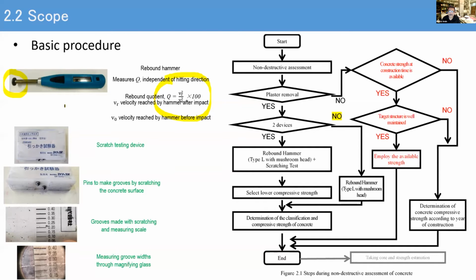And it's not a new device we propose here. It is actually commercially available from many renowned manufacturers. So we chose this device. Another device we chose here is the scratching testing device. It is basically based on the groove width. We apply a specific force through a spring, indent the concrete, and measure the groove width.